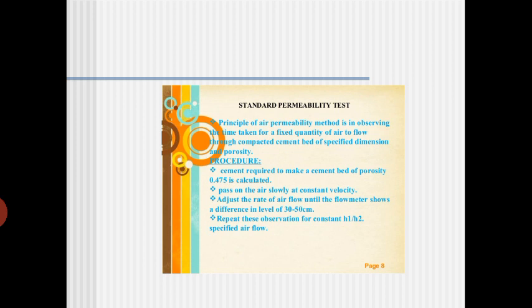Then pass the air slowly at a constant velocity. Then adjust the rate of airflow until the flow meter shows the difference of level of 30 to 50 centimeters. In that instrument, on one side the pressure gauge will be there, and one more, the manometer, will be there. In the manometer it should show a 30 to 50 centimeter level. Then repeat the observation till the consistency head ratio is received, that is h1 by h2. Maybe I'll show you what h1 and h2 are in the manometer, but make sure that the flow meter shows the difference of level of 30 to 50 centimeters.